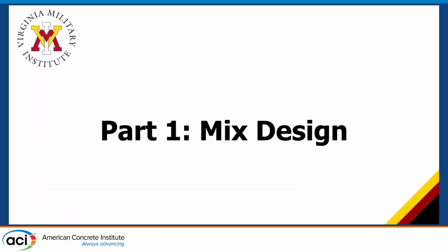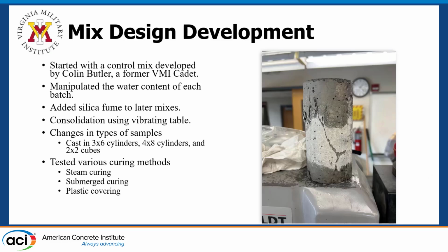So part one, mix design. We broke this project into two parts: mix design development, and the second half, the petrographic analysis. I started with a control mix developed by Colin Butler, a former VMI cadet. He actually presented at ACI last year. I manipulated the water content of each batch and added silica fume to the later mixes. I wanted to get a good control mix at the beginning. And then I consolidated each sample using a vibrating table.